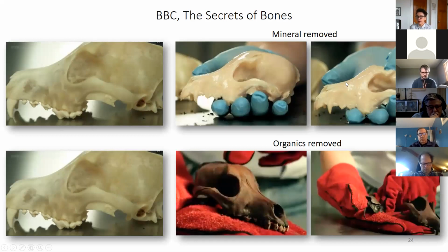They, in the end, behaved absolutely differently mechanically. So the demineralized skull was like a bouncy rubbery ball, and the deproteinized skull was very fragile. But regardless of this mechanical behavior, the shape and the size of bone was exactly the same as in the original specimen. So we know about collagen that this is because of the interspersed phases and branching and twisting bundles